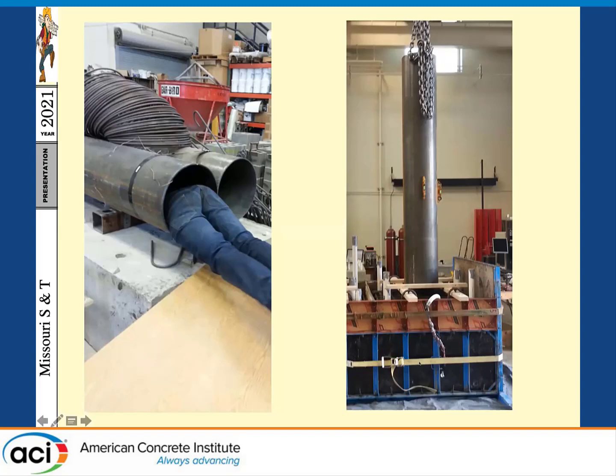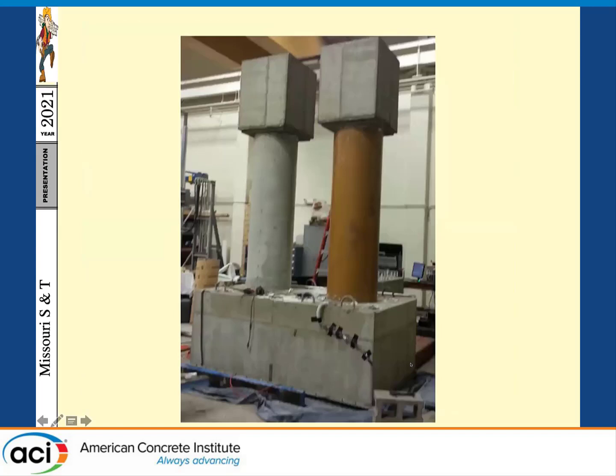We have the formwork for the footing. We have the rebar for the footing. We inserted the inner steel pipe with enough development length. And then the next step is to have the FRP tube and then fill in between the 2 tubes with concrete. The FRP tube was not embedded in the footing. So only the steel pipe is embedded in the footing, and the FRP is terminated, truncated at the face of the footing. So for any moment transfer, all tensile stresses occur on the steel pipe only.